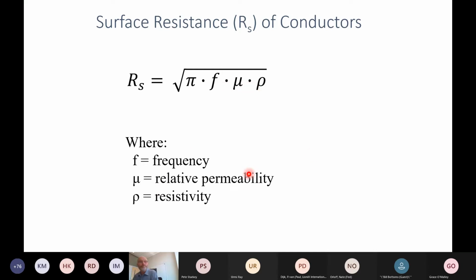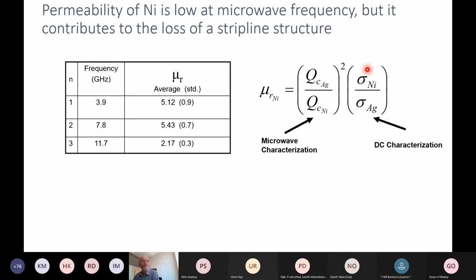That should be permeability, maybe not relative, but it's related to the magnetic properties. Because the rings are identical, it's very easy to back out a very simple formula. If we know the Q factors for these different ring resonators, and we know the DC conductivity, the only really unknown was the permeability.